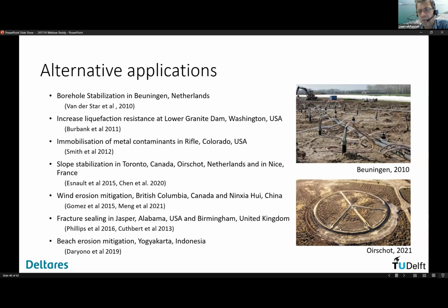Therefore, they wanted to cement the sand. It seemed to be quite a good pilot because, as I mentioned earlier, the cementation is relatively heterogeneous. So you don't want to test it yet in an actual construction site where there are a lot of loads involved. But in this case, the trenches were allowed to collapse slightly, and they just wanted to increase the longevity of those trench slopes, and therefore this process seemed to be appropriate.